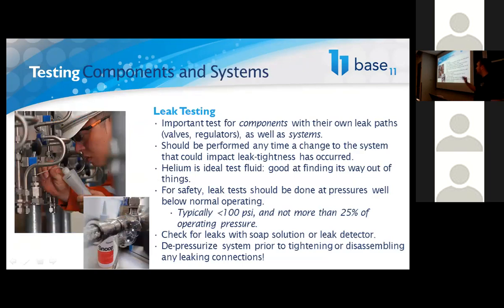Whenever you're doing any of these leak tests, you want to make sure that it's done at a low enough pressure to be safe, because typically you'll use something like helium for this type of testing. Helium is especially good because it's really good at finding its way out of things. And so as a leak test fluid, it's ideal. Plus it is inert, and as long as you're using clean and ideally filtered gaseous helium, you're not likely to contaminate your system with it.